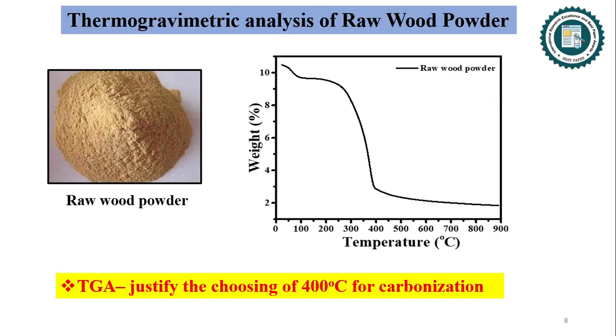Let's discuss the thermal decomposition of raw wood powder of Terminalia elliptica wood by TGA to ascertain the carbonization temperature. Here, the thermal decomposition behavior, that is the TG curve, confirmed that 400 degrees centigrade was the adequate temperature for carbonization of raw wood powder, since no significant weight loss occurred after 400 degrees centigrade, which confirms the completion of the carbonization process.